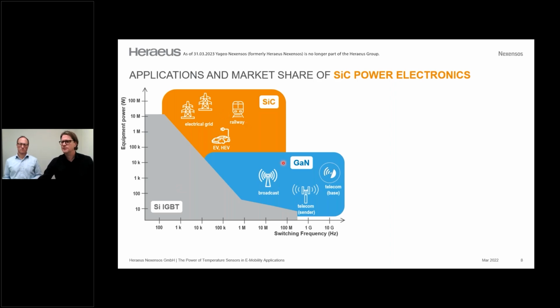If we look at the gallium nitride situation here, it's a bit different for sure. We work not directly with higher power, but we work with higher frequencies for the switching. And if you switch very often in a very short time, this also leads to increased temperature. And this increased temperature is in the end also the problem, and this is why we solve that problem by sintering.